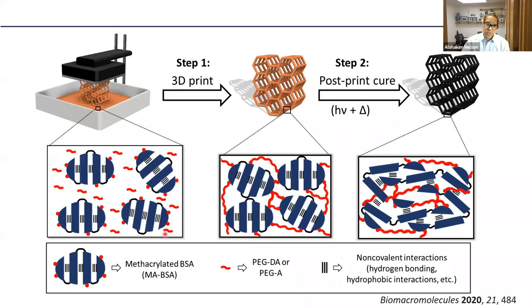So quickly here, what we do is to formulate our resin, and then in the Form 2 printer, we can now print these constructs. An interesting feature about this particular protein resin is that because we're only using light to pattern this material, we are not doing anything to the conformation of the proteins. However, if we thermally cure this material, we can actually denature these proteins. And that helps a lot with mechanical properties because we can transform the largely intramolecular interactions of these proteins into intermolecular ones, and we create a stiffer and tougher material.